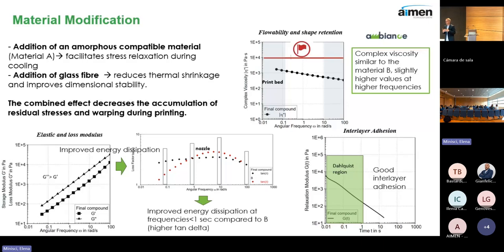And if you look at the graph in the bottom middle, it is a better way to illustrate this viscous nature of the material. This is the tan delta curve, where we are plotting the ratio between the loss and the storage modulus. And what's important here is to look at the low frequency range. Here, the red curve is the original material B, while the black curve is the compounded material, the one that we have modified with fillers and with another amorphous fraction. We see here that the values of tan delta are in the range of 3 to 4, which is ideal for energy dissipation and preventing the accumulation of stresses on the part, and also the